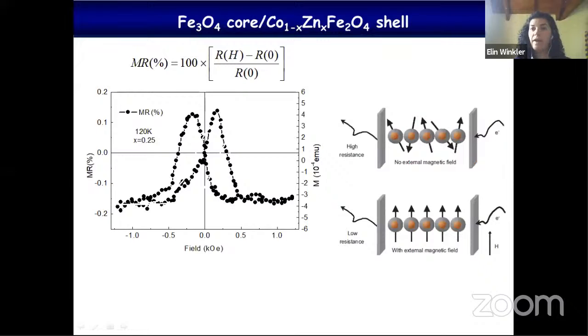And finally, we arrive at the magnetoresistance measurement, where we also observe a maximum. This corresponds to the sample with 25% of zinc in the shell. And again, we observe 2 resistance states: a low resistance state, which we measure at high field, and a high resistance state.